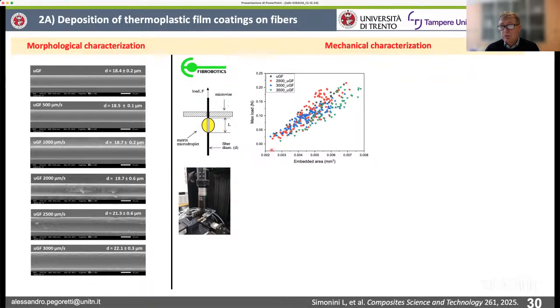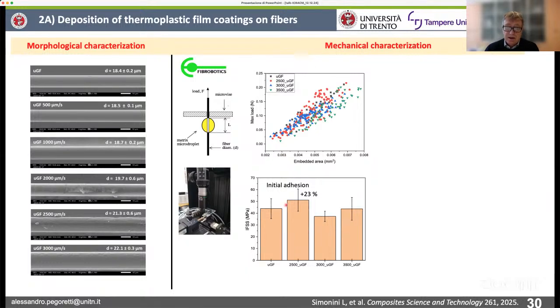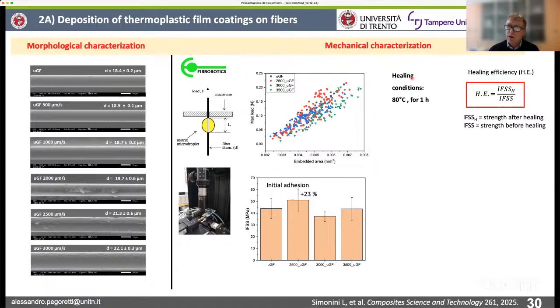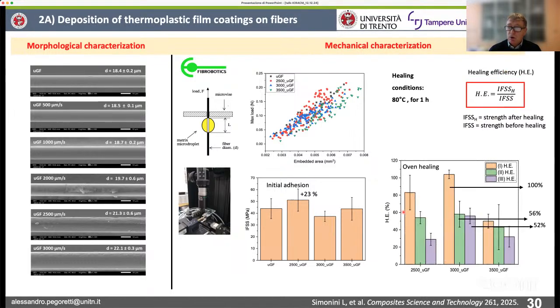Again, by the slope of the regression line used to fit this data, you can get the interfacial shear strength. Here you can see the values. The initial adhesion was actually improved by about 23% by using this condition, a speed of 2.5 millimeter per second in the extraction. And basically, this was a positive thing. So we decided to focus our attention mostly on this condition. And we evaluate the healing efficiency more or less in the same way. So basically, we tested the fibers before and after healing, and we compare the results in a ratio which is called healing efficiency. At this point, we can go into the results.